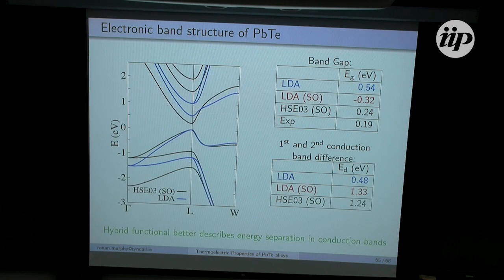Just to show you what happens to the electronic band structure: black is this hybrid functional, blue is LDA, and you can see the inaccurate splitting of the conduction band energies. This was really just to get across the point that in the case of lead telluride, we do need to go beyond, say, LDA and use a hybrid functional to properly capture these electronic properties.